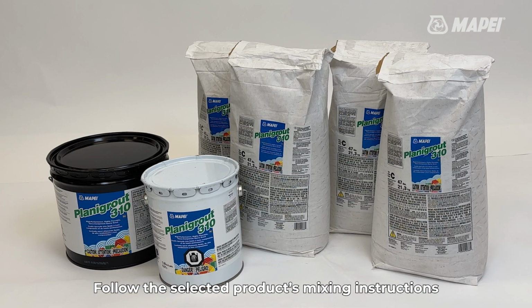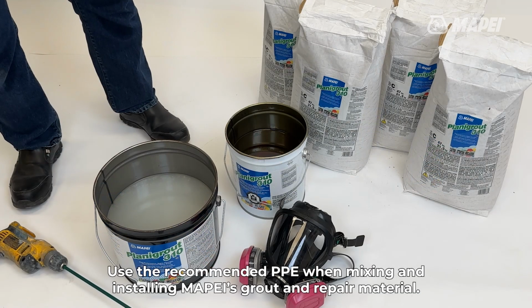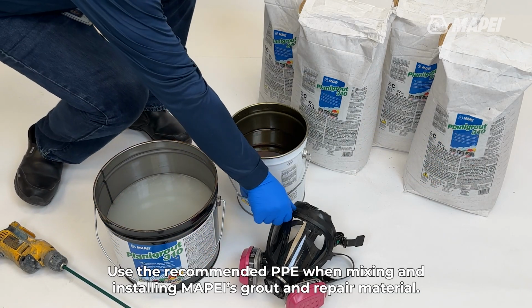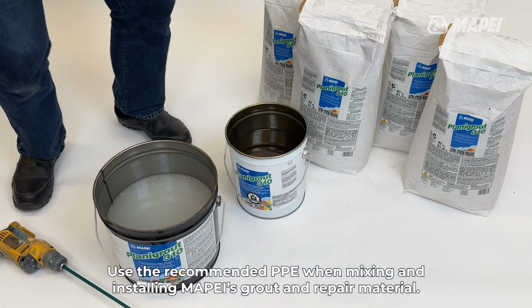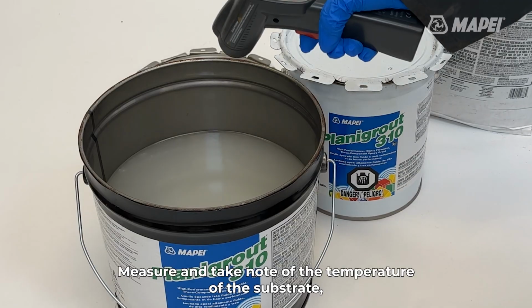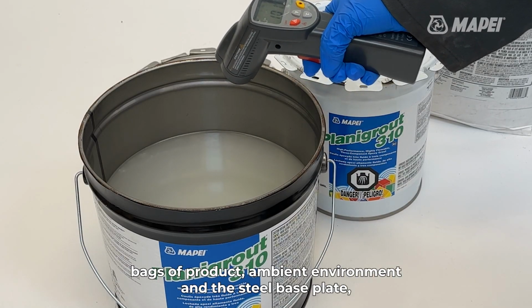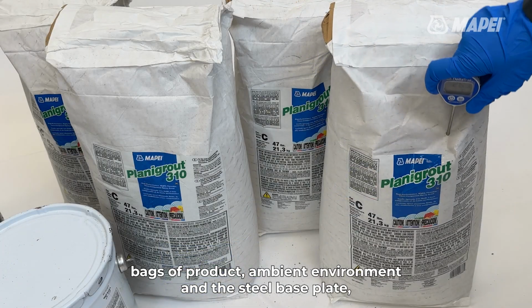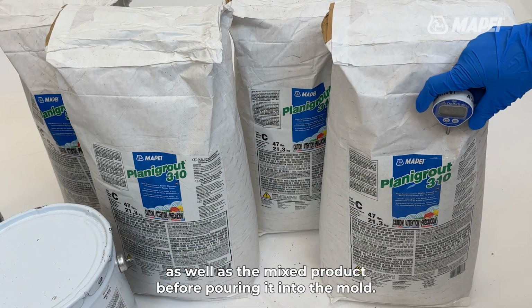Follow the selected product's mixing instructions for selection of the appropriate mixer and tools. Use the recommended PPE when mixing and installing MAPEI's grouts and repair material. Measure and take note of the temperature of the substrate, bags of product, ambient environment, and the steel base plate, as well as the mixed product before pouring it into the mold.